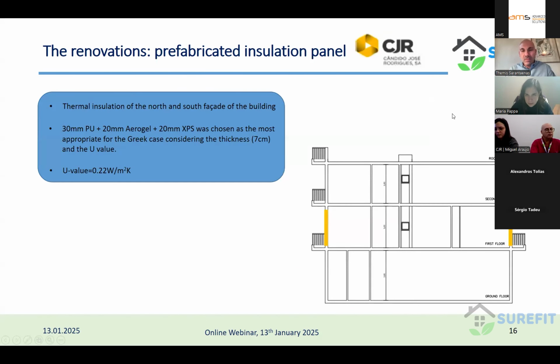The fourth technology is coming from the CJR, that is partner in the Surefit project, and is the prefabricated insulation panel. So the idea was to put thermal insulation on the north and the south facade of this apartment. And it was chosen a sandwich-like panel of 30 millimeters commercial polyurethane panel plus 20 millimeters aerogel blanket commercial plus 20 millimeters XPS panel. The thickness is 7 centimeters because we had this restriction for this building. And you can see the U value of the system, existing wall plus the panel is 0.22.